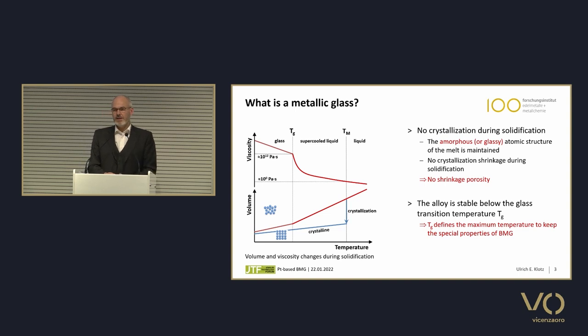So what is a bulk metallic glass? This diagram shows you the properties of a metallic material as a function of temperature. And we see in the lower graph, this is the volume as a function of temperature, and the blue curve shows what happens with the melt when you cool it. When you reach the melting temperature, there is a sudden drop of volume during the crystallization. And this sudden drop of volume causes the shrinkage porosity that we know from casting processes.